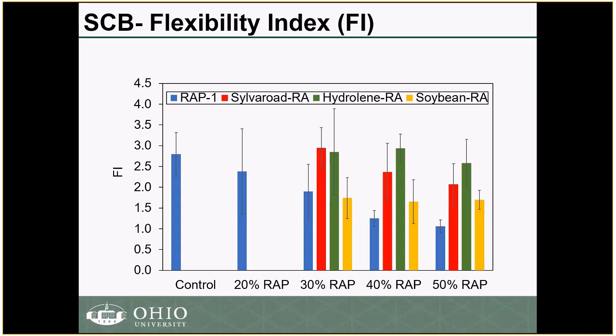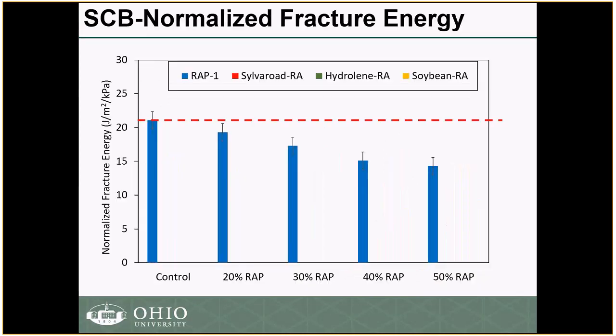The soybean showed good results on the short-term aging, but once we did the long-term aging, as you can see, it did not really show the same improvement that we have seen with the other recycling agents, indicating that soybean might be a softening agent rather than a recycling agent, which is something important to differentiate.